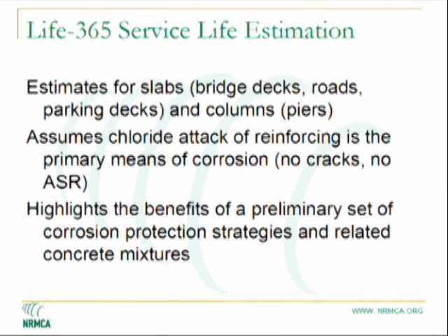The primary mechanism of corrosion in Life 365 is still chloride attack. In other words, it does not address cracks, it does not address ASR and some of the other means of attack. The reason for this is that it is a difficult process from a research standpoint, a laboratory testing process, and trying to accurately capture those effects into equations that can be run in software and a methodology is still difficult.